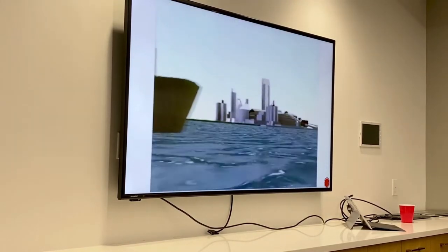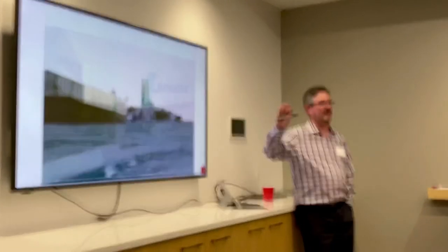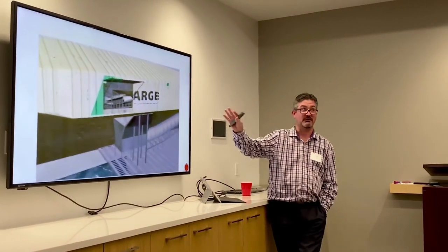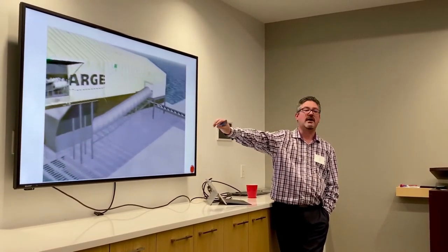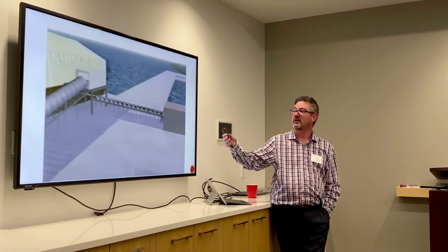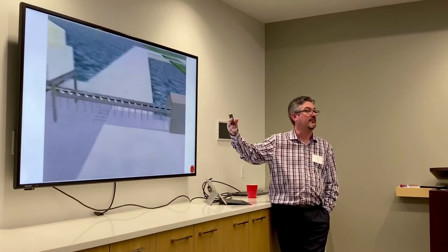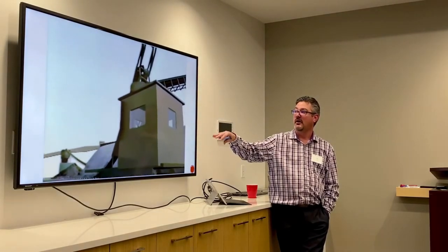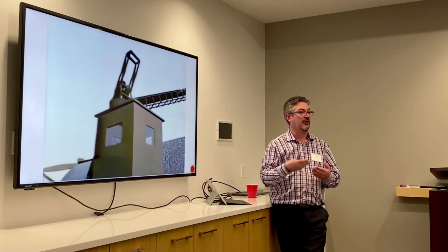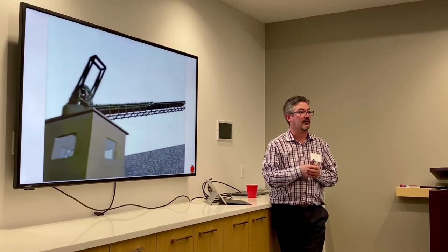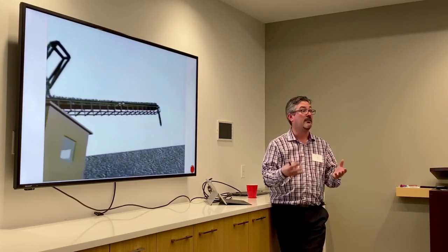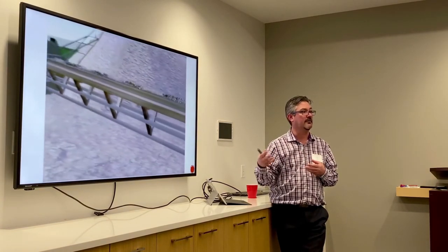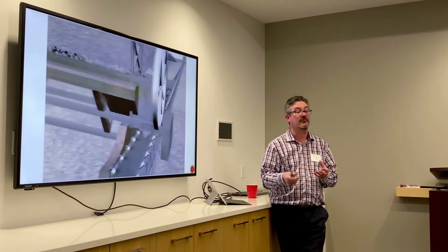Okay, so basically we receive, and this has Lafarge all over it, but I'm not advertising Lafarge here at all, representing the industry, so don't shoot me for that. So we receive limestone at the cement plant, and this is a fairly generic process that's used throughout the world. We put the limestone in piles, and these are called pre-homogenization piles to try and even out the chemistry of the limestone. Because we are creating chemistry here in terms of the reactions that are done inside the kiln, so we want that chemistry to be as stable as possible.